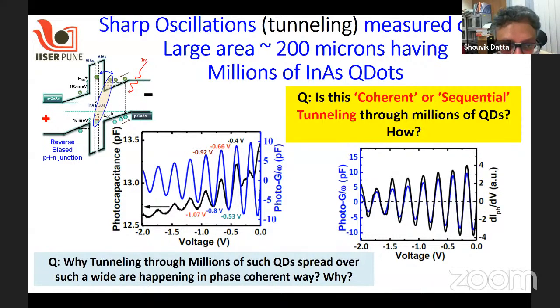But we started worrying, because in all these cases we are measuring capacitance over a very large area, with millions of these quantum dots. So we started asking whether this is coherent tunneling or sequential tunneling through millions of these quantum dots. Why would tunneling through millions of quantum dots spread over such a wide area happen in some phase-coherent way, as it seems when we see these photocapacitance oscillations as a function of voltage?